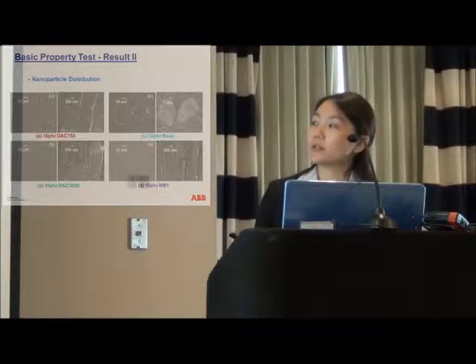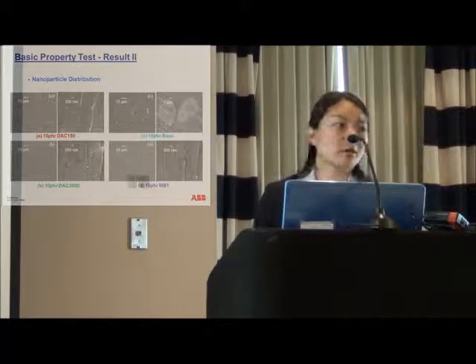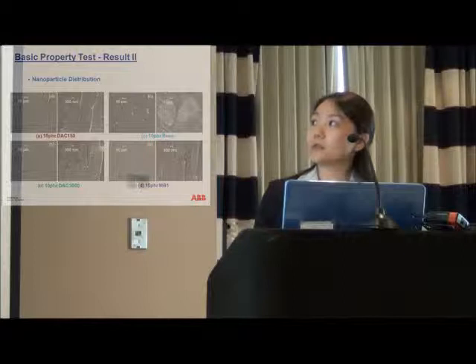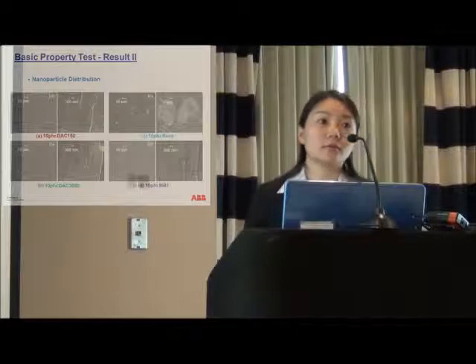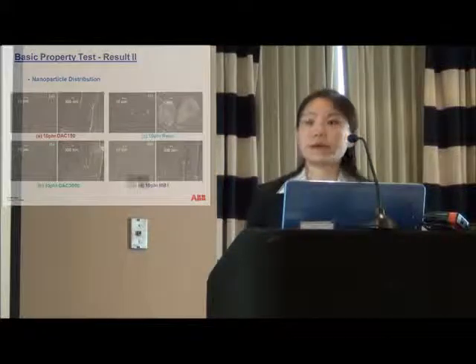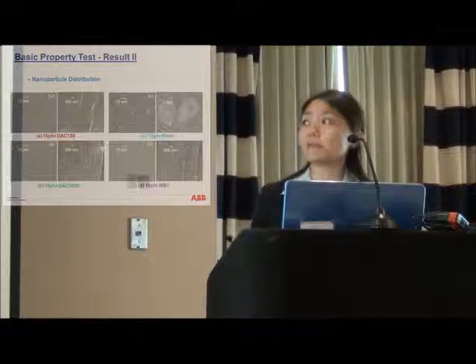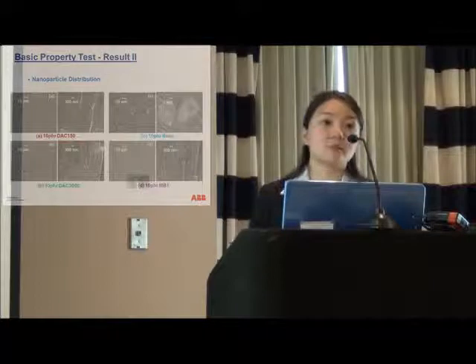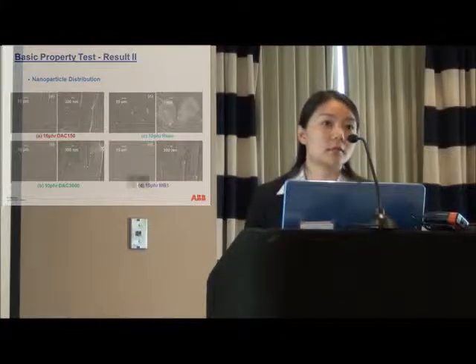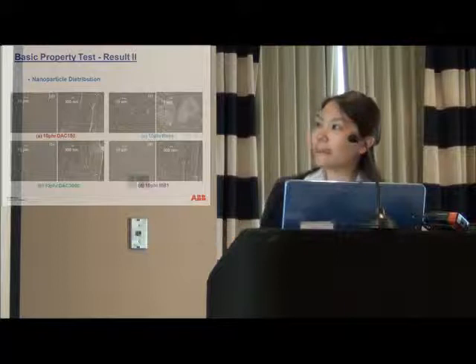The Ross machine with the propeller, the high shear mixer, shows very big aggregates actually - between 5 to 6 microns and even 10 microns. It was very difficult to break those aggregates of particles.